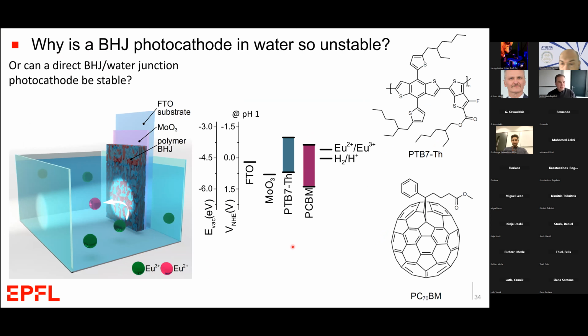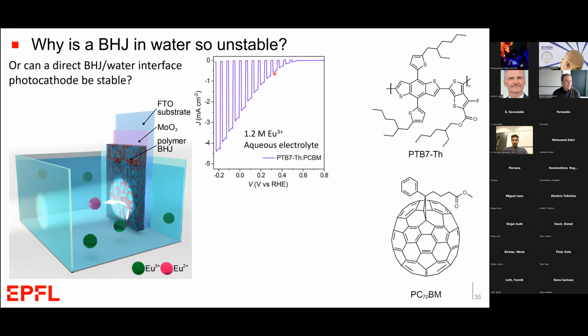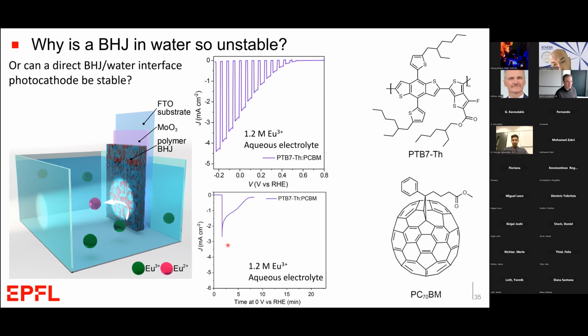We first looked at this with these two materials as a donor and an acceptor, which have a little bit higher performance than the other materials that were shown on the previous slide. And while we do see some reasonable photocurrent here under these sacrificial conditions, when we try to run this as a function of time, the photocurrent quickly degrades down to 0. In fact, in only 10 minutes, we see a very poor performance.